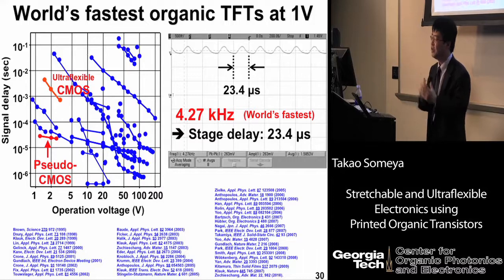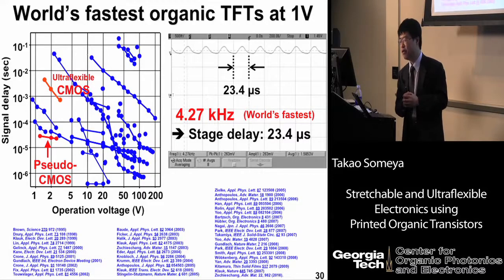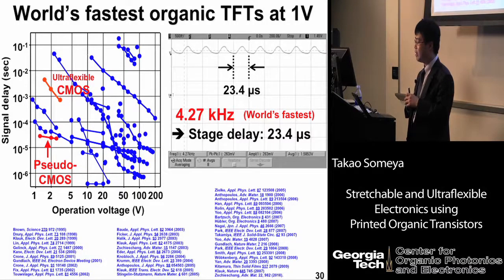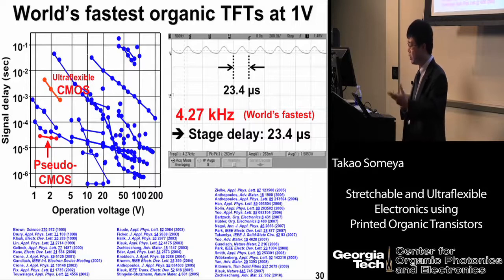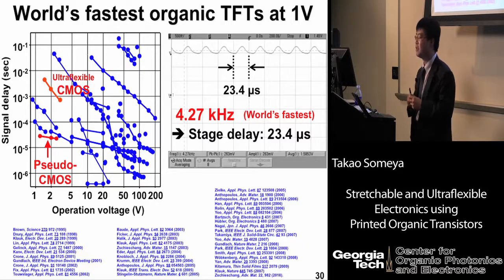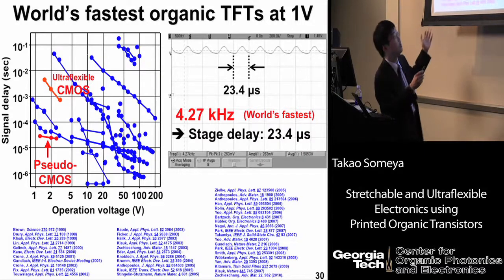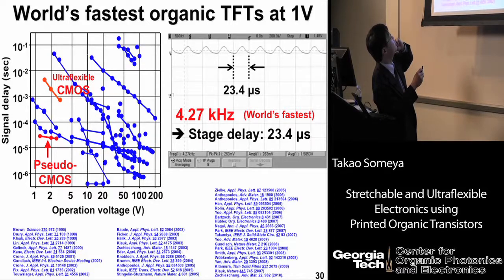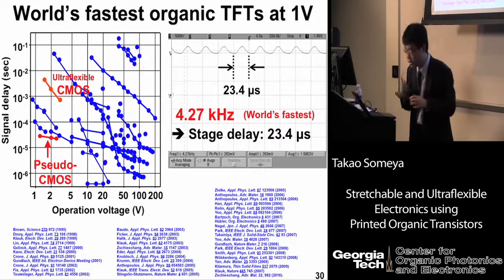By combining the pseudo-CMOS and high mobility organic semiconductors, we now achieve the world's fastest organic TFTs with an operation voltage of 1 volt, and the oscillation frequency becomes as large as 4 kilohertz. And this is the literature value. So now we could significantly improve the frequency, by 2 orders of magnitude compared with the conventional CMOS layout.